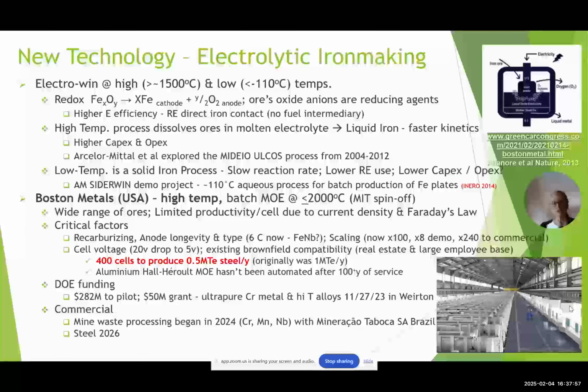So, electrolytic iron making, there's high and low temperatures. The redox is simple. The iron oxide gives iron at the cathode and oxygen at the anode, and the ore's oxide anions are the reducing agents. The high temp process dissolves ore in the molten electrolyte, giving liquid iron, technically faster kinetics, but also much higher capex and opex. ArcelorMittal and others explored the ULCOS process from 2004 to 12.